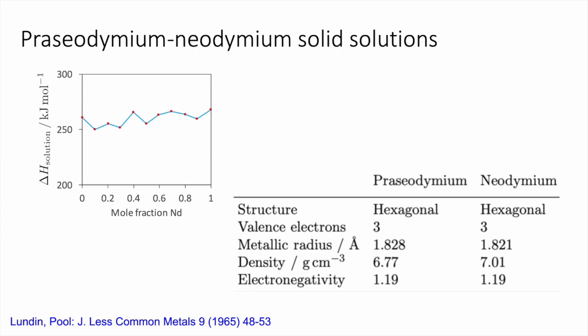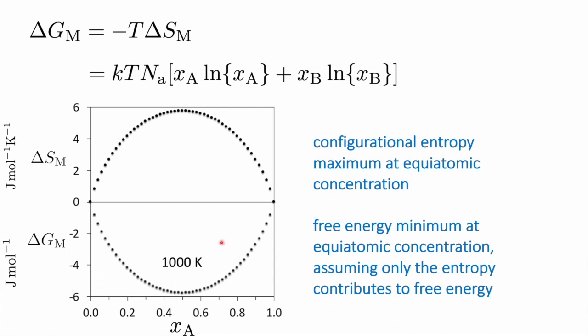But in reality, there are very few solutions which are ideal, in other words, have a random mixture of atoms. So this free energy of mixing that we calculate from the entropy of mixing of an ideal solution is not likely to be the correct representation of the free energy of a real solution, where you do get changes in bonding when you break AA bonds and BB bonds and form two AB bonds. So we need to have a more sophisticated equation than this.